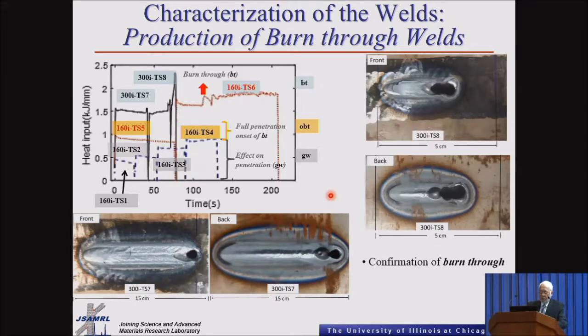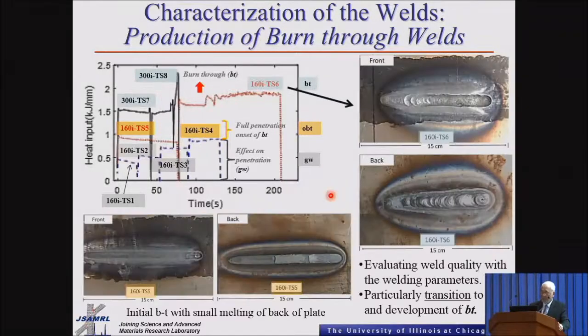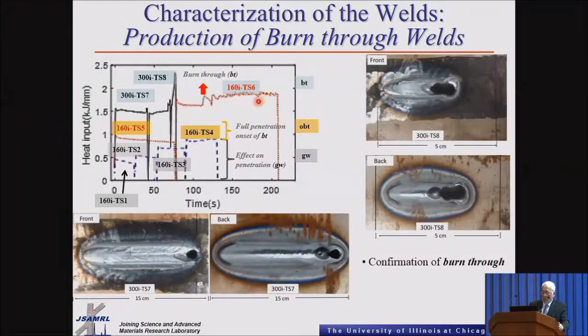Now in the case of, let me go back to this one over here. This two in here, we have the burn through, and this one is burn through. But in between, when we have the weld contained, there will be partial penetration, full penetration, but the onset of burn through. Now, when you go to the very high heat inputs, and right now what we're looking at is the high currents of 300 amps, you can see the holes are really being formed, and you have burn through. So now what we have done is try to characterize or to correlate the heat input with the production of a burn through.